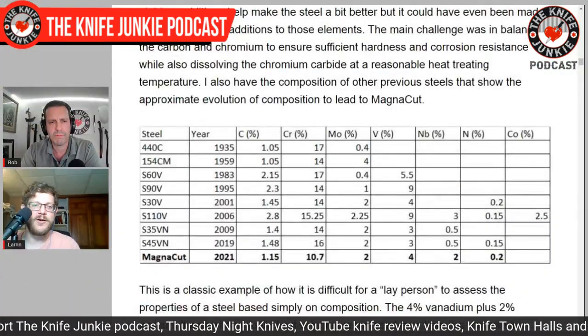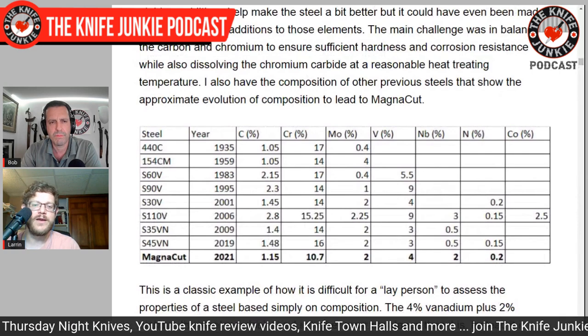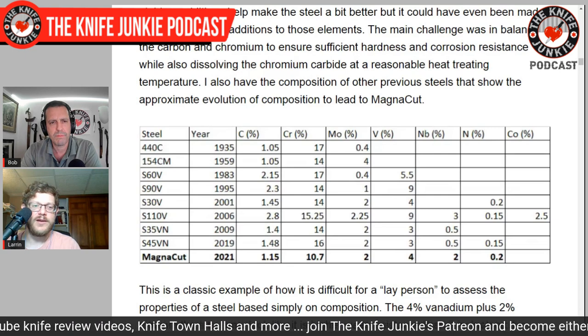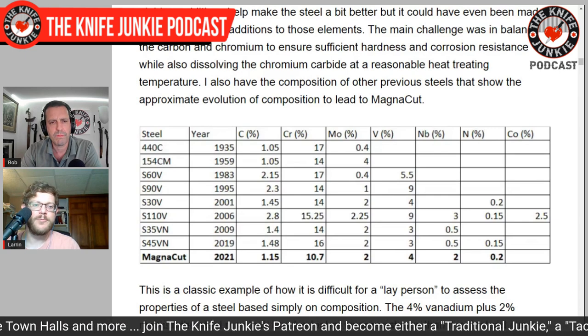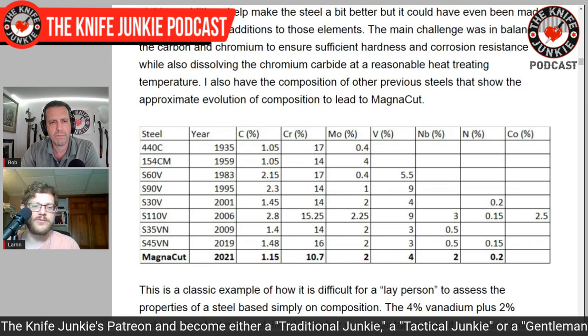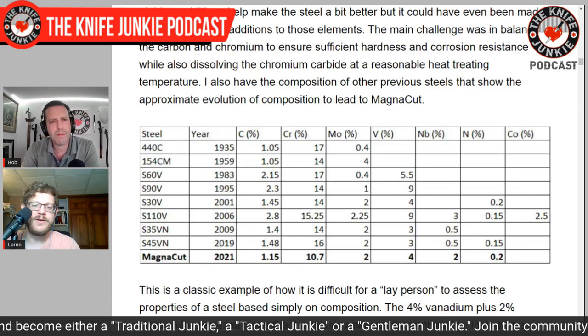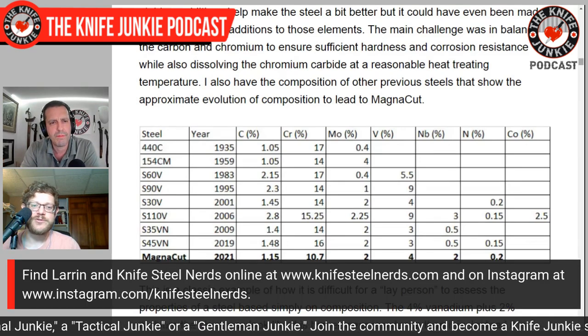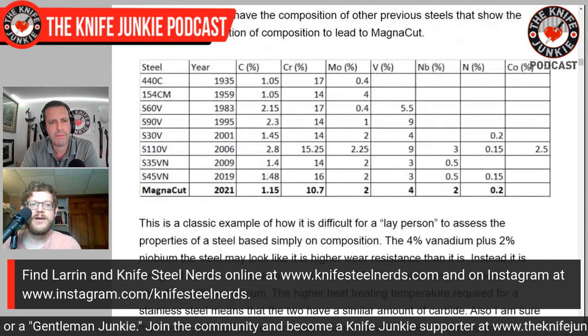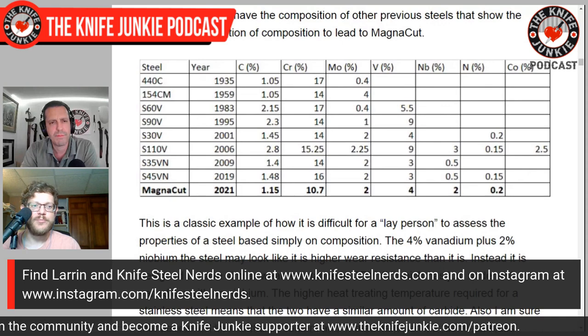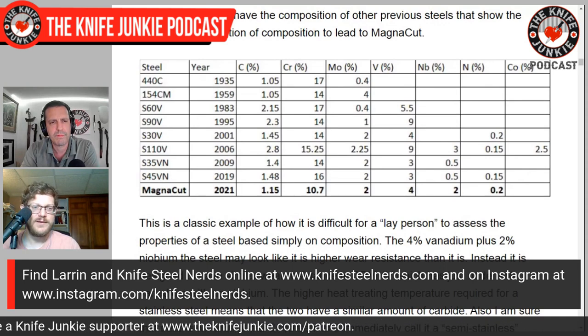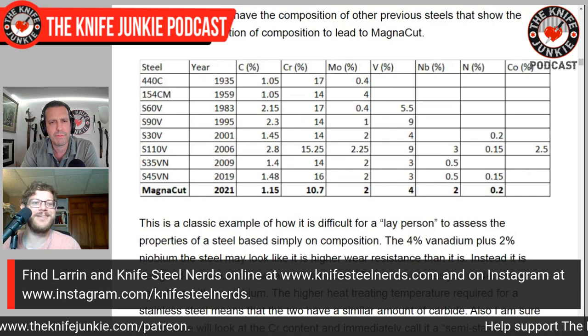And the rest of that chromium is just going to chromium carbides. And the chromium carbides are not as effective for getting your high properties as just a vanadium or niobium carbide. So a steel like CPM-4V has only vanadium carbide. And that allows you to have better properties than the stainless steels that have a lot of these softer chromium carbides in them. The chromium carbides are softer and larger. They're larger, which reduces your toughness, and they're softer, so you get less wear resistance for a given amount of carbide. So with the harder, smaller vanadium carbides, you get better properties. So all I did was reduce the chromium. That's all you had to do, a piece of cake. You just balance the other elements so that you get the right amount of carbon for hardness, the right amount of chromium for corrosion resistance.